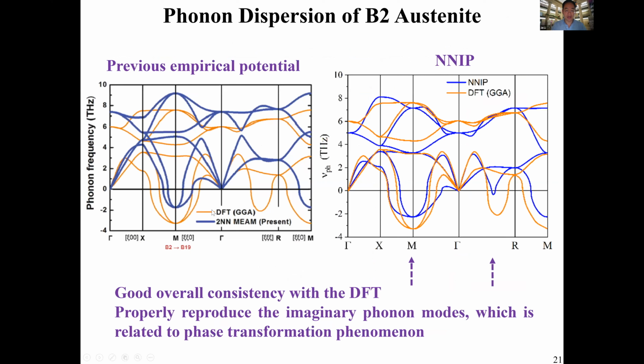The key is the phonons, as I mentioned, because the vibrational entropy is a very key part. There was previously an MEAM potential. This modified embedded atom potential is able to reproduce the imaginary phonon frequency at the endpoint, compared with the DFT density functional perturbation theory calculations. But it's not able to capture another phonon instability branch between the gamma and R point, in the R direction. Whereas with the neural network potential, without intentionally fitting this particular phonon, we are able to reproduce this phonon instability.